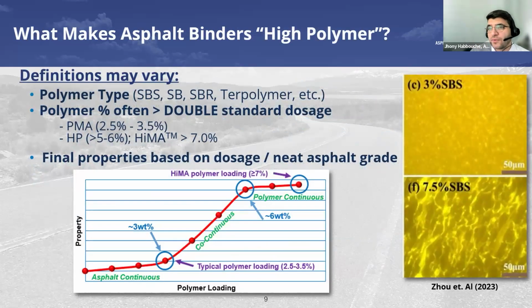Now, the question becomes, what makes an asphalt binder a high polymer? And that's a very tricky question because it could be answered from several perspectives. First of all, polymer type makes a huge difference. Second, the polymer content also is a key factor here. If we compare our typical polymer modified asphalt binders, these are the conventional ones that we use on a daily basis. These typically are modified with 3 plus or minus 0.5% polymer. When we start talking about high polymer modified asphalt, these typically involve about 5, 6, even 7 percent polymer.